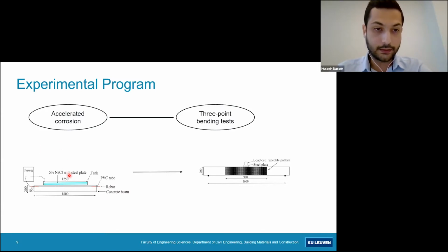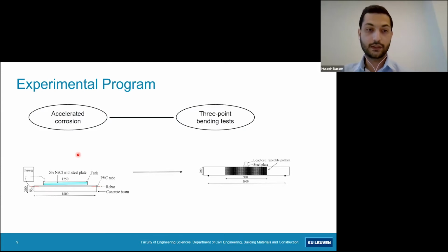A tank containing salt solution was glued to the cover using silicone, and a steel plate was immersed inside the salt solution. Both the rebar and the steel inside the salt solution were connected to a power source so that the corrosion reaction can start. After the corrosion reaction started, formation of damage in terms of pits along the rebar and cracking parallel to the rebar occurred. 3 corrosion levels were targeted in this experimental program, namely 5%, 10%, and 15% of mass loss or cross-section loss of the steel.